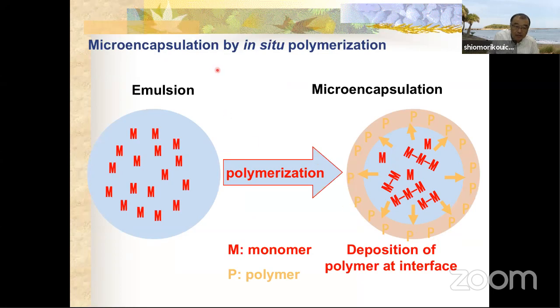The formation mechanism is shown here. First, the in situ polymerization method. Initially, a monomer is dissolved in organic solvent, and after making an O/W emulsion, the mixed solution temperature is raised. Radical polymerization starts, and the monomer changes to dimer, trimer, and polymers. The polymer is deposited at the interface between the organic phase and aqueous phase to make the wall of the particle.